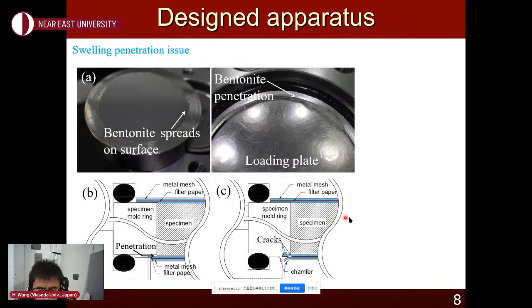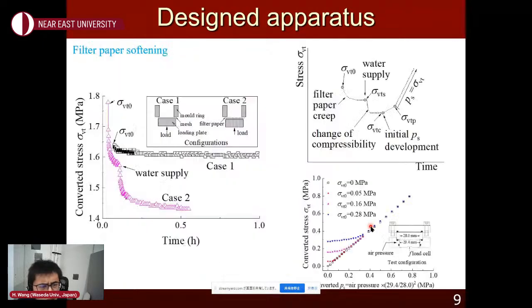There are some problems when we conduct the test. For example, because of the filter paper compression problem, sometimes we found that due to the swelling, some bentonite was squeezed out, like here. So for this problem, we try to refine the apparatus to increase the manufacturing accuracy to remove this kind of problem.